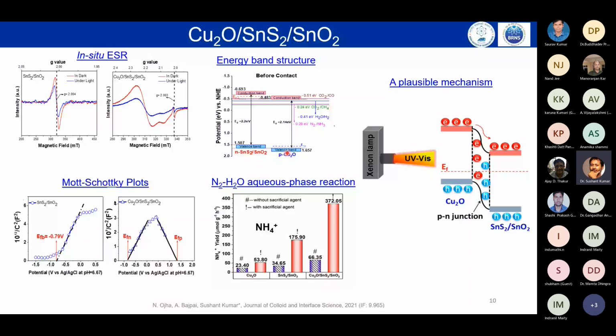Now, we also performed the reaction for nitrogen and water in the aqueous phase, and in the aqueous phase we saw NH4+ forming. We tested with and without a sacrificial agent, and the way we measured the quantity was Nessler's reagent. We concluded that whenever we use a sacrificial agent, there is interference from the sacrificial agent in making a precise measurement of the ammonium ions. So these were our observations, and then we tried to understand the possible mechanism.